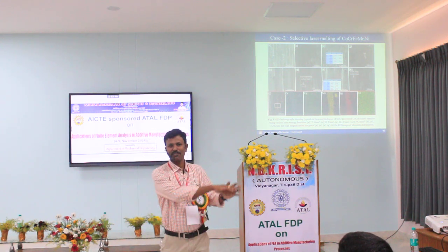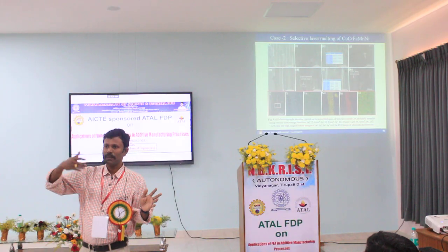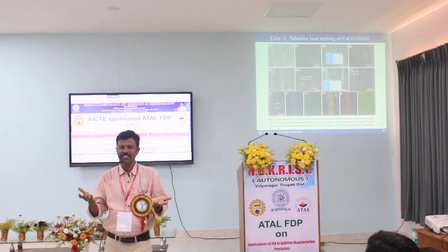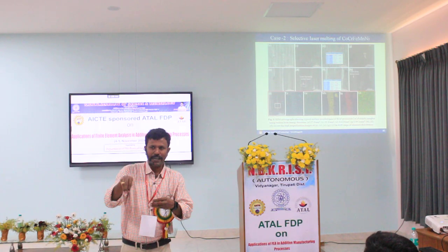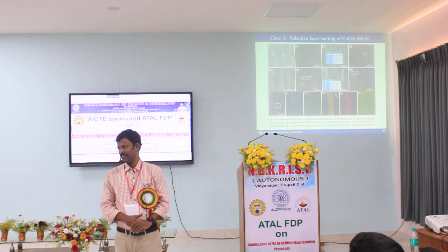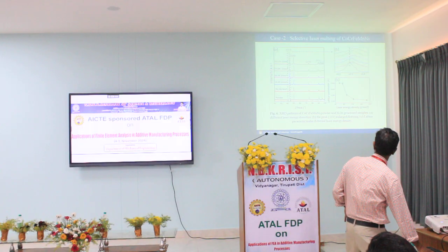Then again we started from scratch, analyzing all these things. There are parameters like laser head shaking or bed shaking techniques we used to adopt, thereby breaking down the elemental segregation, and finally we optimized it. That's why it took almost 1.5 years.